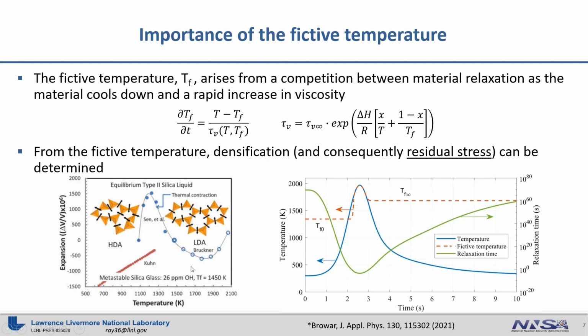And in fact, depending on how you terminate the heat source, that viscosity may be increasing very rapidly, which basically traps the fused silica structure in some orientation that's different from the initial equilibrium orientation. And the point where that structure gets trapped is kind of what we call the fictive temperature. In other words, the fictive temperature is a metric to describe the state where the fused silica got trapped. So the fictive temperature is not something where I can take a thermometer and measure it. Rather, it describes the state of the fused silica. But the fused silica is in this densification regime, which is governed by the fictive temperature.